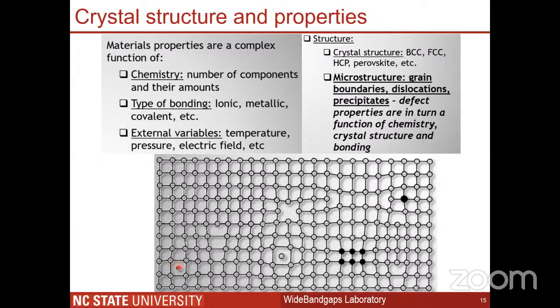So it's zero dimension. But now, if you turn your attention to this defect here, this is an example of a one-dimensional defect. What this looks like is that you have removed a half plane of atoms from this area, right? And in doing so, you create a one-dimensional defect in the crystal. It's called a dislocation because it seems like you have dislocated the crystal halfway by creating this defect. And you can see that it has also changed the bonding around it significantly. And as I'll be showing later, such defects also change the properties of the semiconductor material drastically.